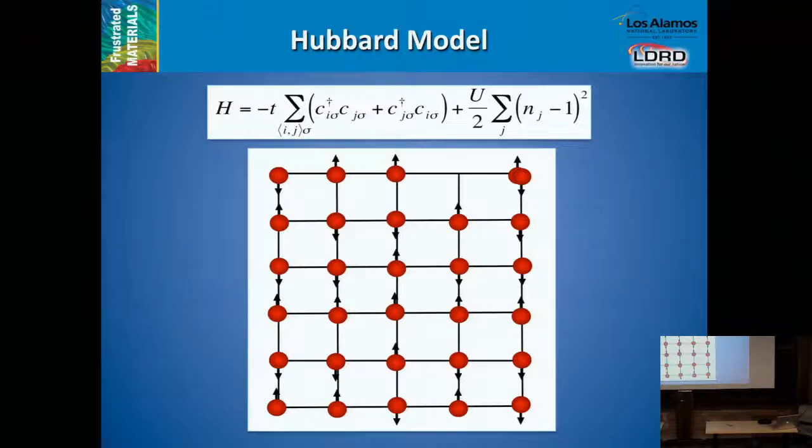But of course, as I was saying, to zeroth order, if you put the hopping to zero, if there is no kinetic energy, then you have 2 to the n degenerate spin states. But as soon as this hopping becomes finite, which is the realistic situation, you can do perturbation theory in the ratio between T and U, that is the dominant interaction.